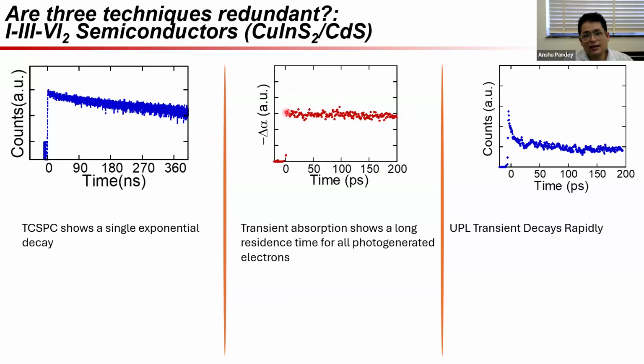What transient absorption says is, well, at t equal to 0, I have my pump pulse, or the main powerful blue pulse, which I had earlier, arrive, and this kicks quite a few electrons into the conduction band. In fact, it's been tuned to kick around 1 or less than 1 electron into the conduction band per quantum dot. So once this electron resides there, the absorption of the state decreases. That's exactly what is being shown, and because of which we get this very nice flat line. And it's a really flat line, which means indeed after the pump pulse arrives, for this duration of 0 to 200 picoseconds, nothing much of interest is happening. The electron is just happily sitting in the conduction band and doing nothing. It's great. Now we look at UPL.